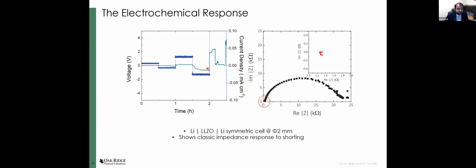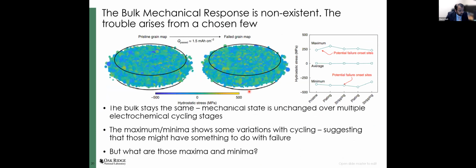So when we cycled these solid electrolytes in situ at the beamline, we showed a typical electrochemical response: when increasing the current density applied to the solid electrolyte, we see polarization fluctuations and the impedance going to 0, which is consistent with shorting of a cell. But what was interesting to us was that the bulk grain maps did not show any stress associated with this